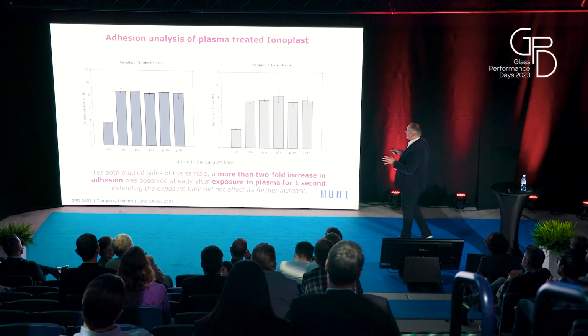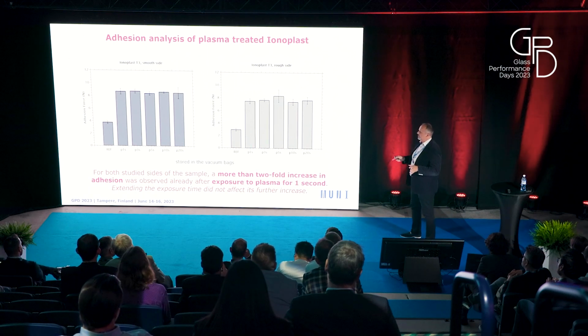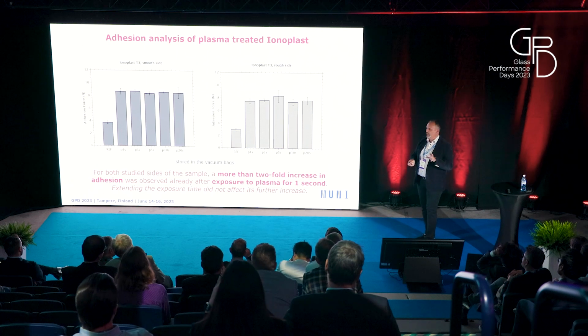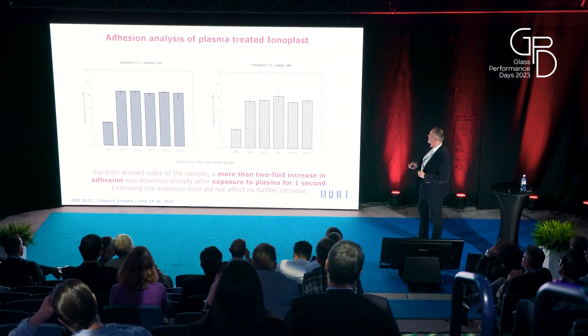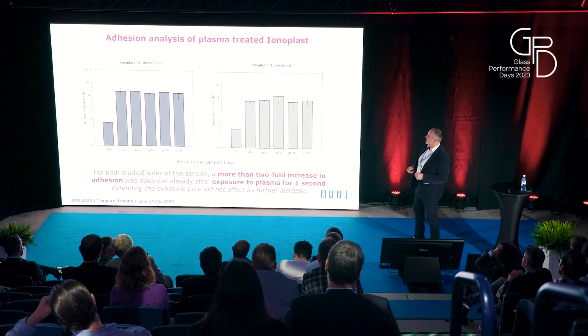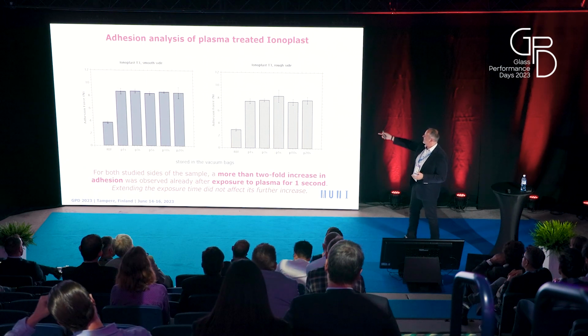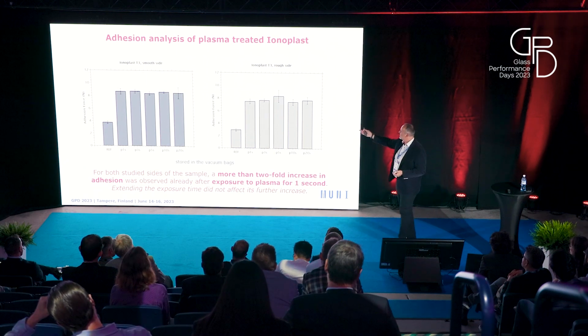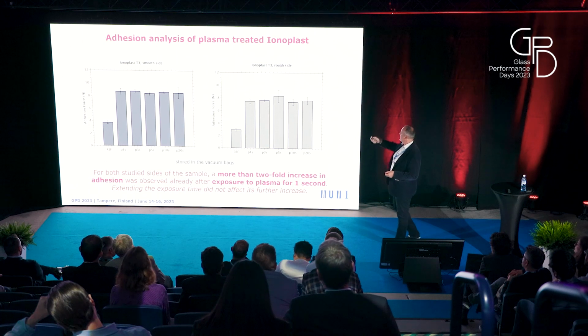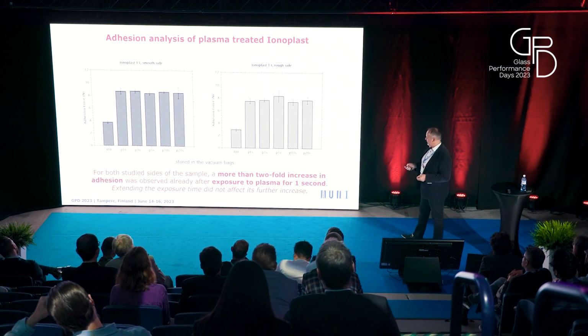Also it is interesting, if you remember, I mentioned that the optimal exposure time was 5 seconds for water contact angle measurement, but adhesion is a complex problem. We can see that 1 second is quite sufficient from this point of view, and we observe the saturation.